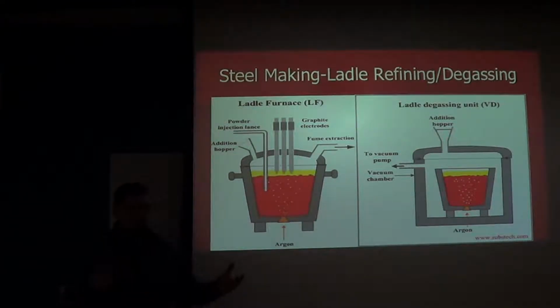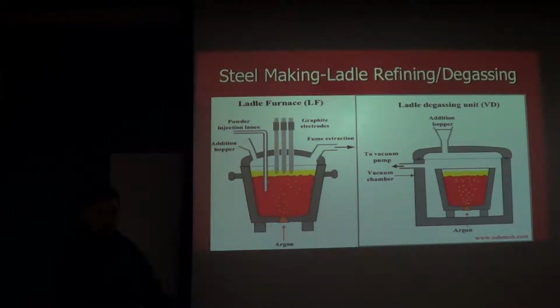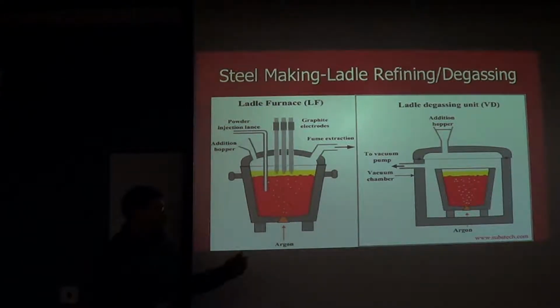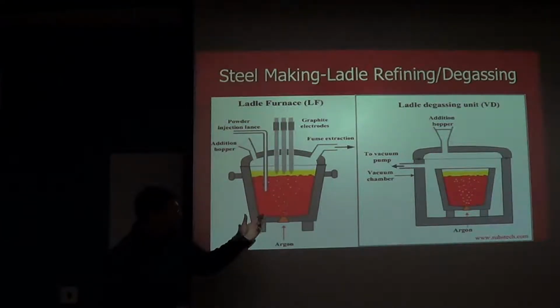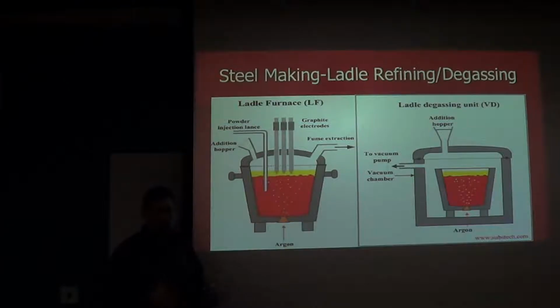nitrogen, hydrogen. The way that's done is to take that ladle, and it's quite large, and you put it into a container that you can put a lid on and actually draw a vacuum. And while the ladle's in the container, you've got a mechanism to stir the material so that you can expose all that liquid metal to that vacuum environment.